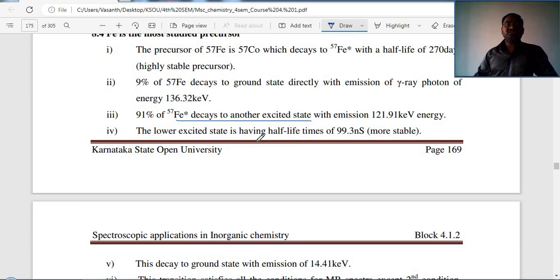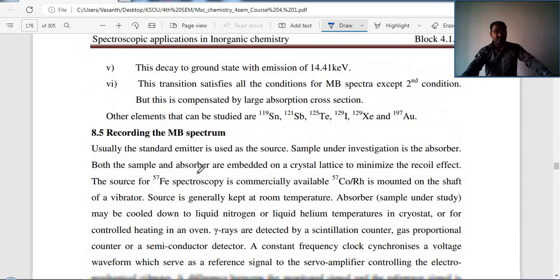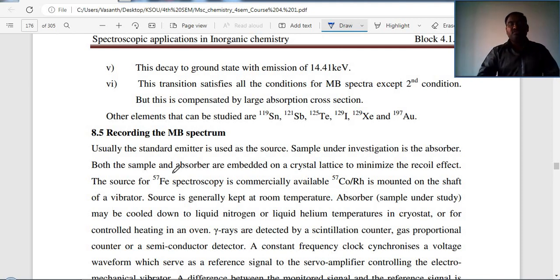The lower excited state has a half-life of 99.3 ns. This decays to the ground state with emission of 14.41 keV. This transition satisfies all the conditions of Mossbauer spectra except the second condition, but this is compensated by a large absorption cross section.